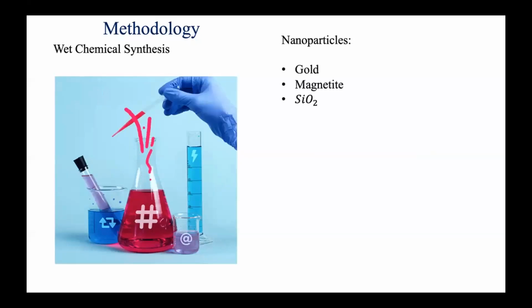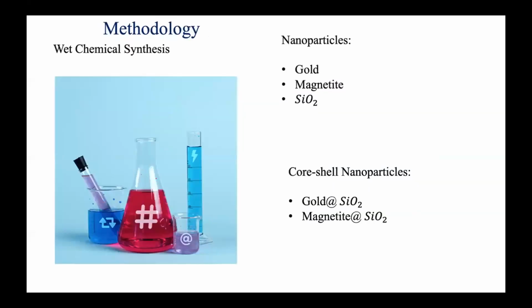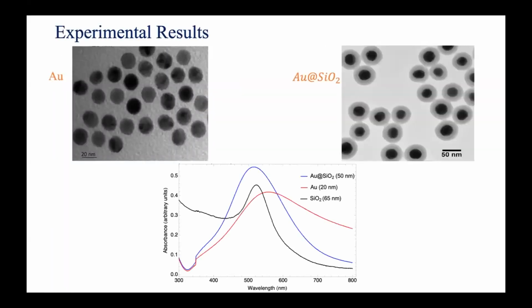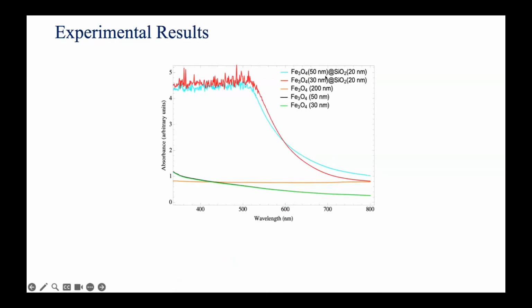Now when I go to the lab, I have to make this type of nanoparticles, the core-shells of gold, magnetite, and silica. With the experimental results, from the absorbance spectra we see that gold absorbs at around 500, but it gets broader, absorbing a broader spectrum when you coat it with silica. And here we can also see that when you put silica on magnetic nanoparticles such as magnetite, we also see that it starts to get more absorbance.